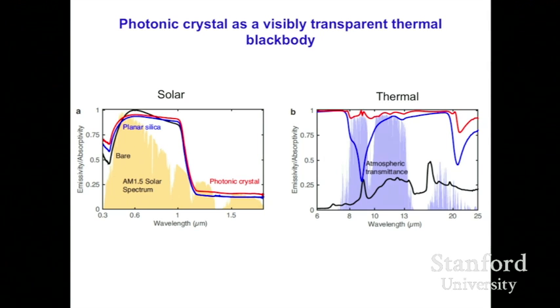On the left here is the absorptivity as a function of wavelengths in the visible and near infrared. And you can see strong absorption of all 3 structures in frequency above silicon band gap, as you expect. The absorption property of all 3 structures are actually fairly similar. And in fact, the photonic crystal structure has a slightly higher absorptivity compared with the bare silicon region due to the light trapping effect I've been talking about.